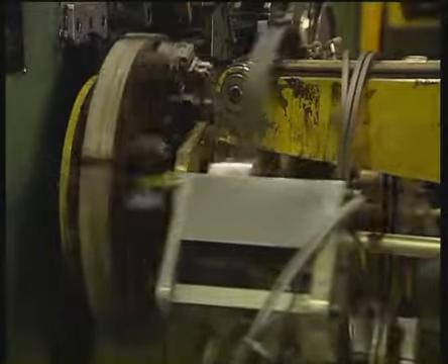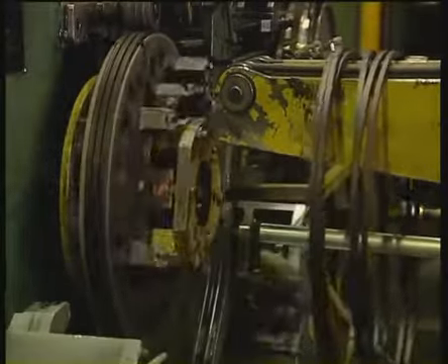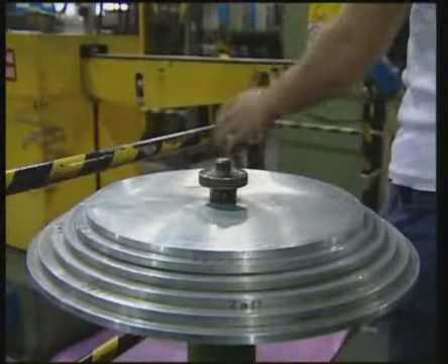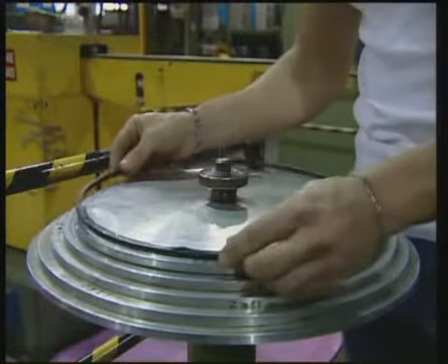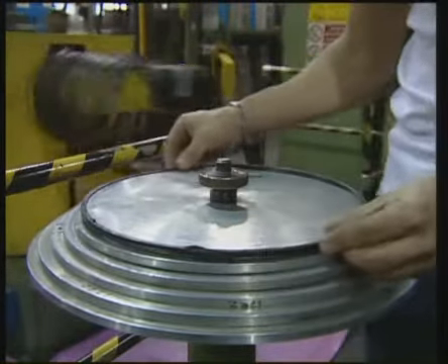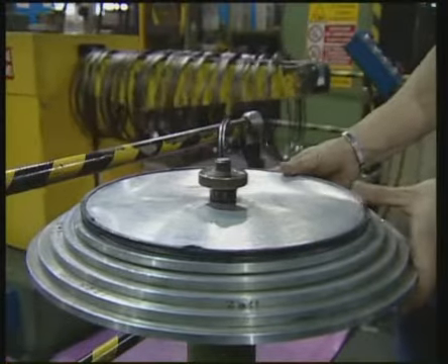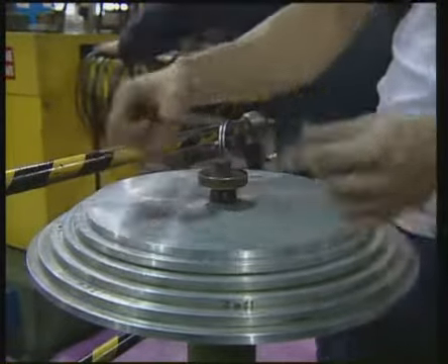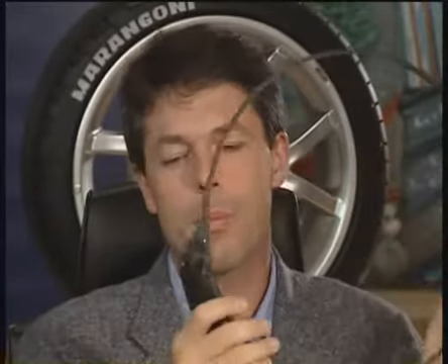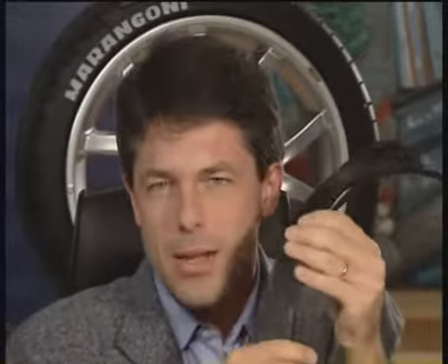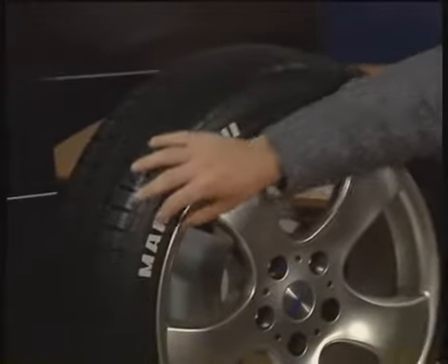To check the precision of the diameter of the bead wire, randomly selected samples are fitted on steel rim templates. A simple check that gives certain results and is very quick. A rubber substance in a roughly triangular shape is then applied to the bead wires prepared as described before. It is the filler. The filler is made from a special, very hard compound, which is used to make this part of the tire, the bead, more rigid.